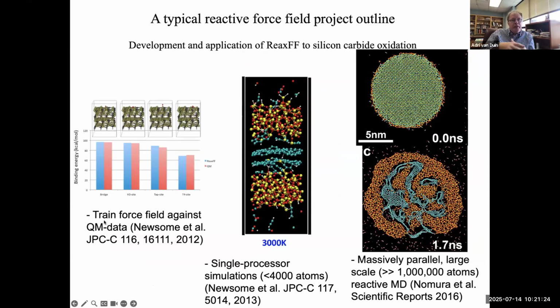Our training sets are typically a bit smaller than the data sets used by neural networks. So typically we use something like several thousand data points rather than millions of data points. But we very strongly focus on particular chemical events, like for example here, oxygen binding at various sites of silicon carbide, oxygen migration, and transition states.